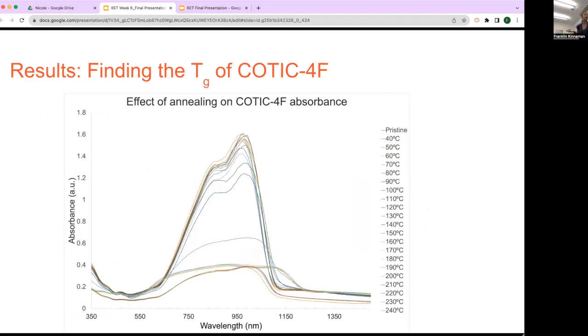So what did I find in my results? This is the raw data, so this has not yet been normalized, but you can still see qualitatively what's going on here. The first thing that's pretty obvious is that at temperatures above 150 degrees Celsius, we saw a super steep decrease in the intensity of the absorbance of the material, so complete loss of the integrity of these peaks. And then also at 120 and 130, that's still a pretty sizable gap between all those other peaks that come above it.